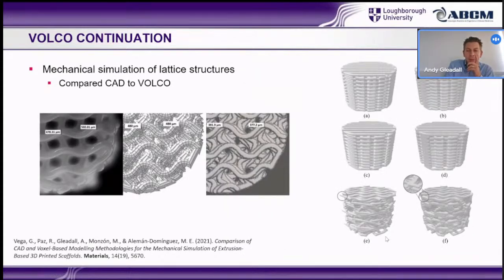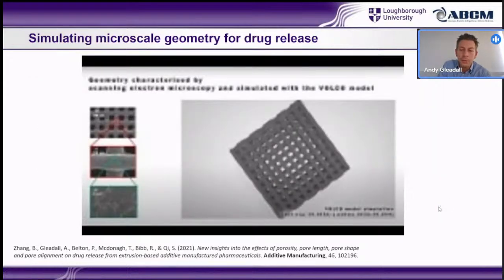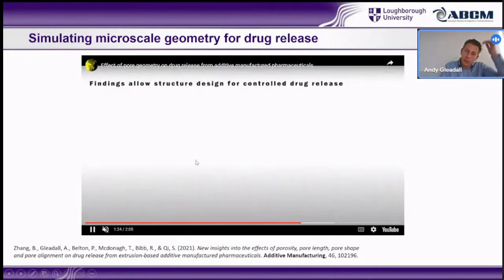Then another use of it was to compare to a better approach at CAD modeling. The one I'd shown before was state of the art at that time. Then 3 years later, someone had developed an alternative way to generate CAD models based on the toolpath, and they did a nice comparison to the CAD model there. Volco was better sometimes, the CAD model was better at other times, but it was an interesting study to show that there is this point that needs to be considered, which is how well you're able to get a prediction of your expected geometry based on the toolpath.